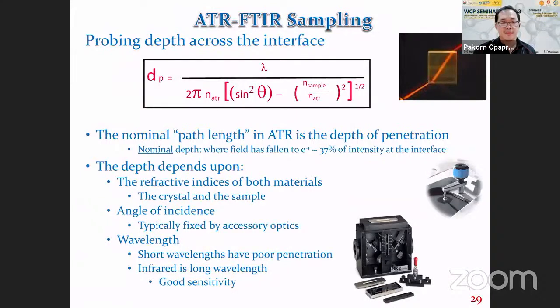Now, if you look at ATR again and look at this equation, this is the depth of penetration of the wave. Normally, we get signal from the surface and then go deep into the sample. How deep depends on this equation, which depends on three factors that I already mentioned: refractive index of the crystal, wavelength, and also angle of the beam.